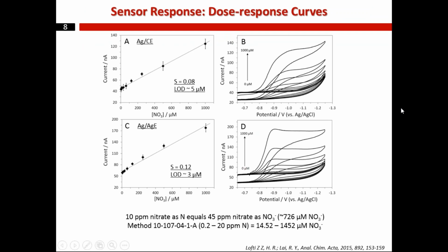Then we studied the response of the sensor toward concentration of nitrate. And we did this by introducing different concentrations of the nitrate to the sensor and collecting the corresponding voltammogram. Then we calculated the peak current for the CVs, and we showed that as a function of concentration of nitrate. And in this way, we generated the calibration curve for the sensors.